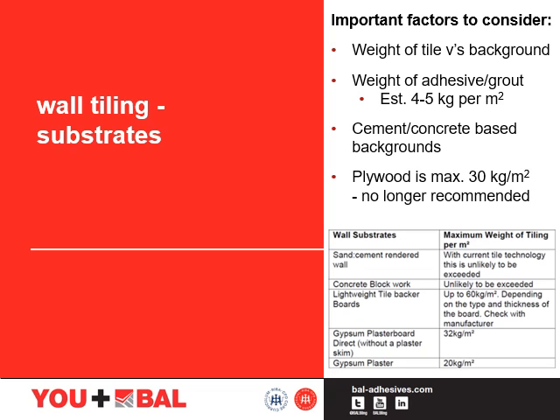Adding the 4 to 5 kg per square metre of the adhesive and grout, we have between 34 to 35 kg per square metre on average. As you can see from the table, tiling onto gypsum plaster or gypsum plasterboard is not acceptable as it exceeds the weight limit on that substrate. We should also always consider specifying a lightweight tile backer board, which can take up to 60 kg per square metre depending on the type and thickness of the board — always check with the manufacturer. Please note plywood is no longer recommended in the British standards for wall tiling.